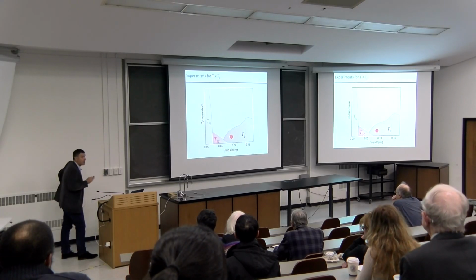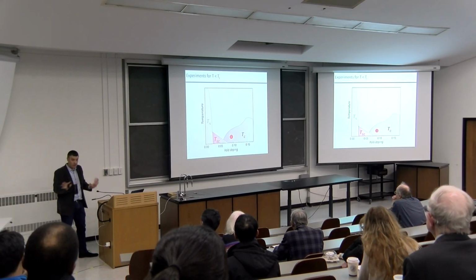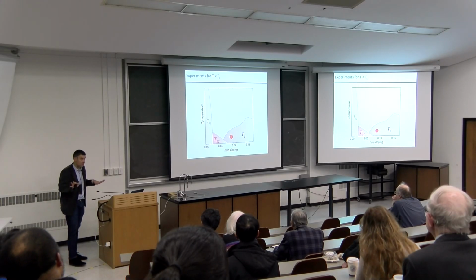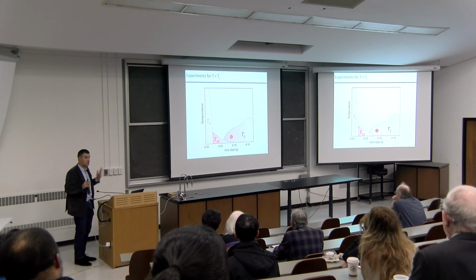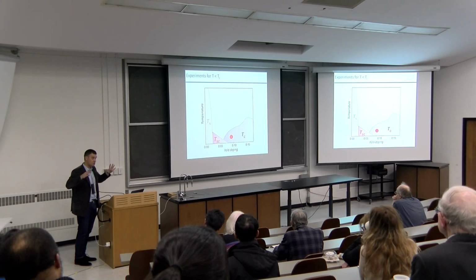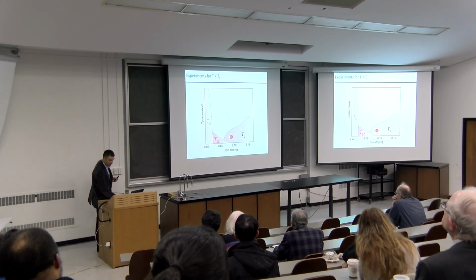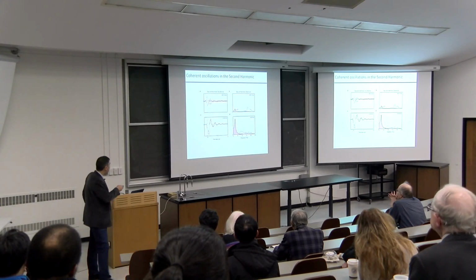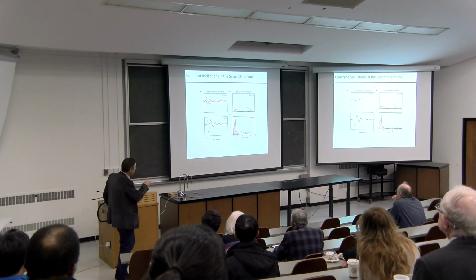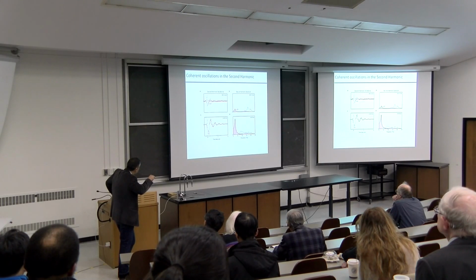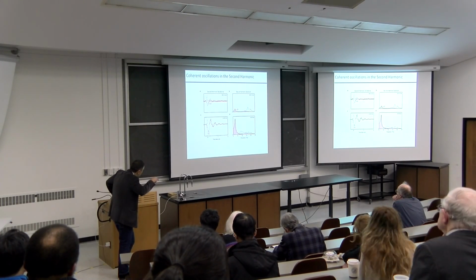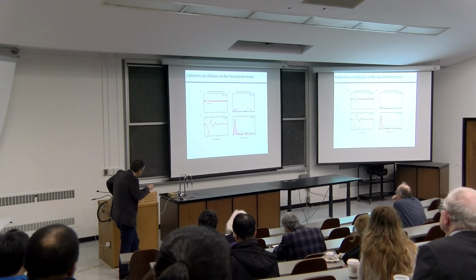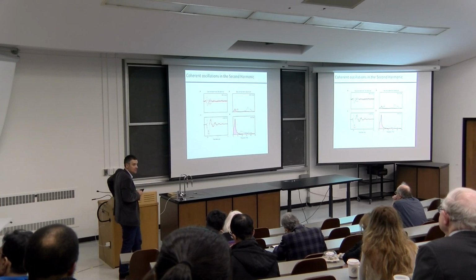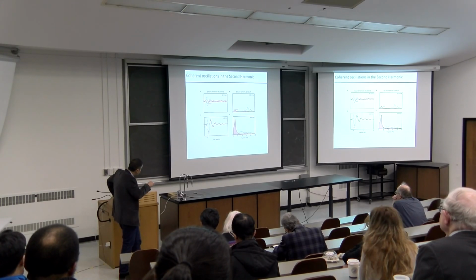So now let's first check whether what these guys say is real. So we go below TC, where there's preformed superconductivity. We know that there are these superconducting plasmons, J1 and J2. We know what the phonon is, and we just want to know whether we are really generating coherent supercurrents driven in this way. So sure enough, what Alex showed is that this is data. You pump the phonon at low intensities, say 0.5 megavolt per centimeter. This is my pumped phonon, which then rings for a while. But if you Fourier transform this, you will find that these are two pumped modes for reasons that I won't tell you. This thing decays into two modes which are somewhat at the sum frequency of which matches the yellow. And when you go to larger amplitudes, these two guys decay into this and into a huge peak at low energies. Okay?